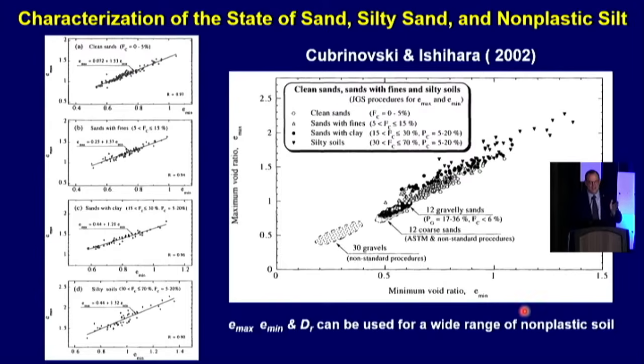They looked at that and used this kind of statistics to prove to an unready audience that, no, we can use relative density beyond 5% fines. We can go to 30% fines. Then when I met him, it was more like 30 to 40% fines. And after working together, we started realizing, if you really look at the data, you can go to 70% fines.